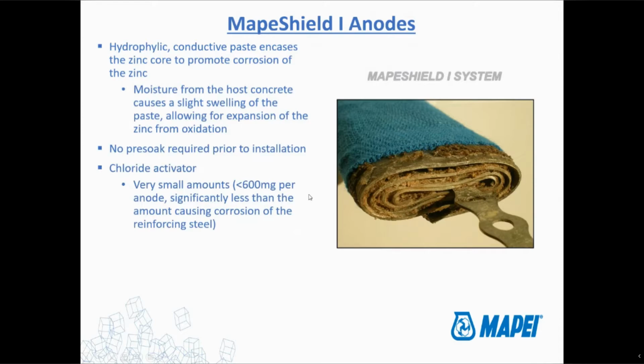You have to use something to cause the anode to start, basically to turn it on, to flip the switch to on, if you will. So that one manufacturer that doesn't use chlorides uses pH. You have to be at like a pH of 13.5 or higher to get their anode to turn on. And what we have found in testing is that you can't maintain that high of a pH. The second you open the anode and expose it to air, it starts dropping down almost immediately. So what we found is those anodes never turn on. They just stay passive, and you may as well not even put them into the patch. So they just don't work very well. That's why everyone else is using chlorides, because we know that they work.